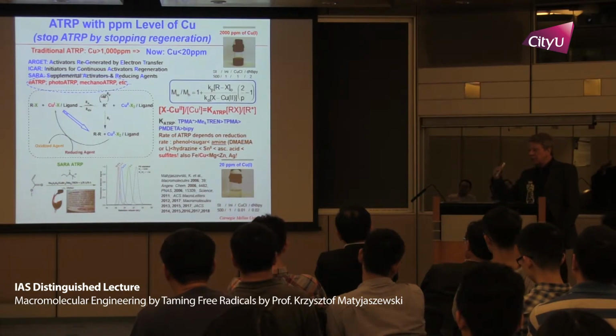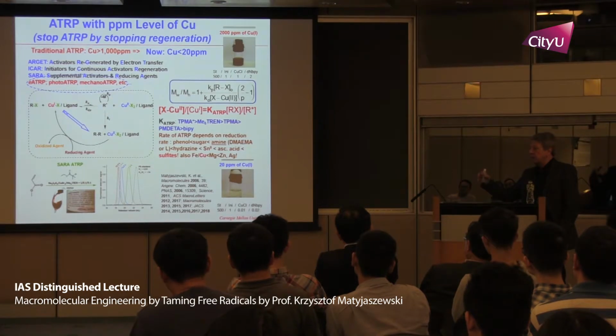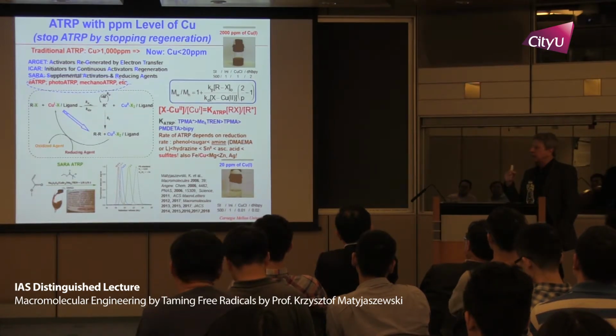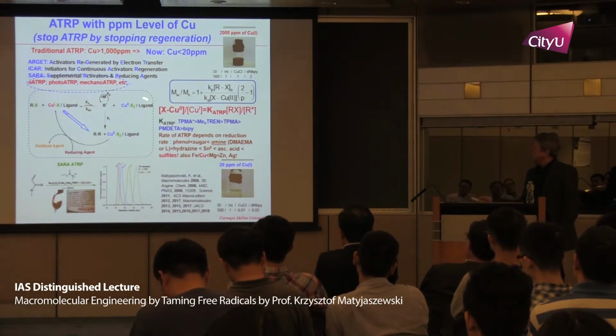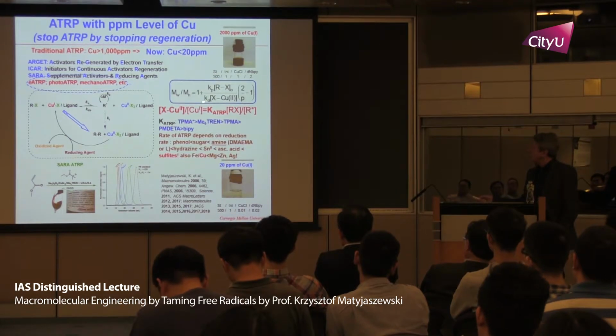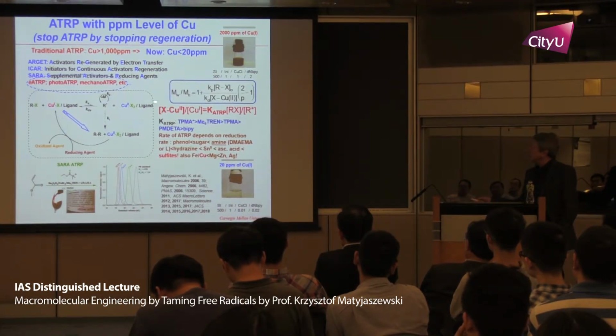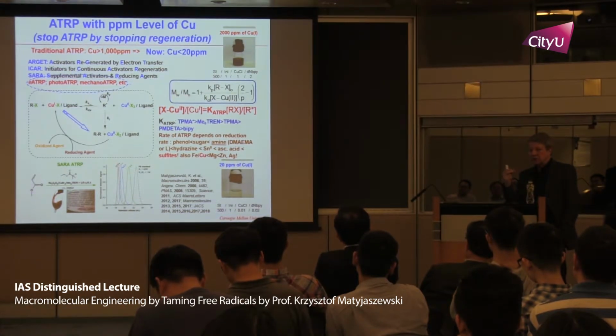If I go to lower and lower concentration of copper, 100 ppm, 50, 20, 1 ppm, I would like that all of this copper is in the form of copper 2 rather than copper 1. And this depends on equilibrium constant. If I have a large equilibrium constant, I have a larger fraction of copper 2. So what we want to do is really to use larger and larger equilibrium constants.